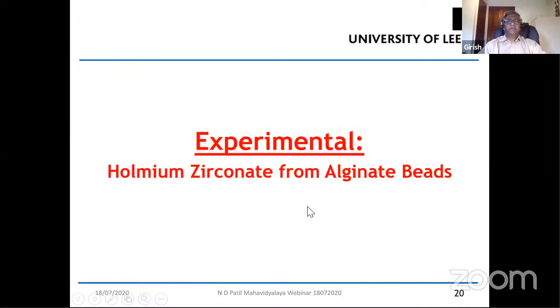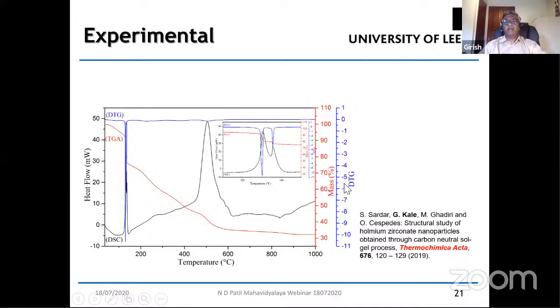So we looked at holmium zirconate, which was prepared by the process that I mentioned before. Again, around 500 Celsius, you can see the last weight loss that we get in the TGA DSC data, where there's a complete transformation of the initial precursor into fully crystalline holmium zirconate nanoparticles.